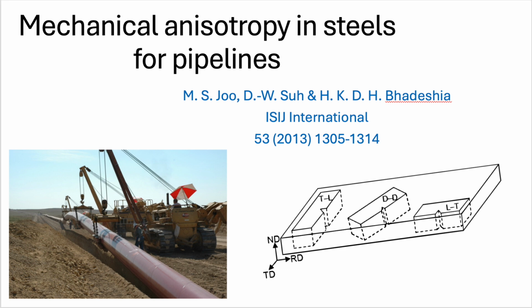Sort of, yeah. Take manganese sulfide, MnS. It's relatively soft at rolling temperatures, so it either deforms and gets stretched into long, flat shapes, or it breaks up into lines of fragments. We call them stringers. Stringers, and these create weak planes. They do. Think of that like wood grain, easier to split along the grain. Same idea here. The fracture toughness is measurably lower when you test it in a way that the crack can easily follow these stringers. It's pretty wild that microscopic bits of sulfur residue can compromise a massive pipeline, and the tests confirm this difference in toughness based on orientation.